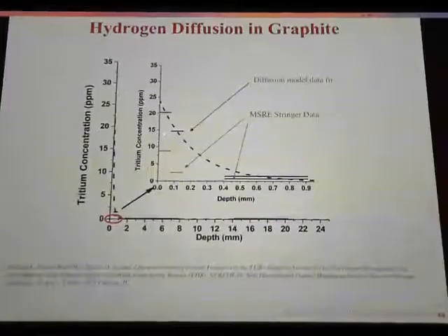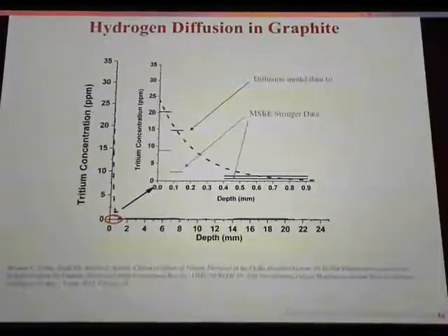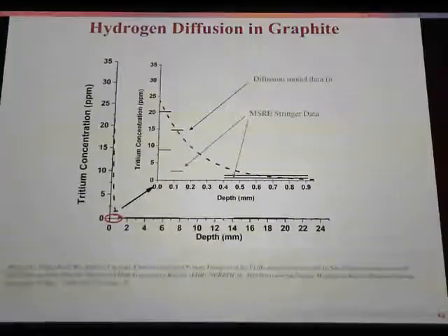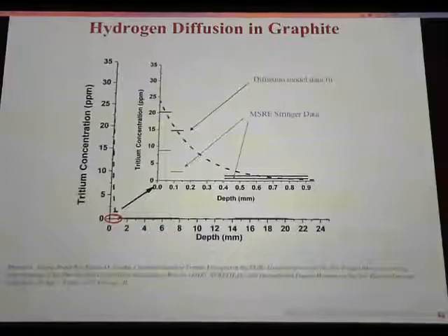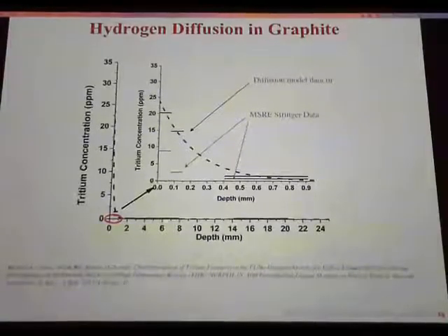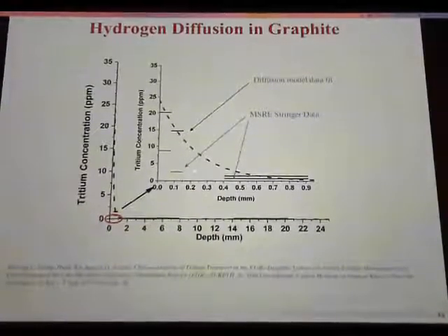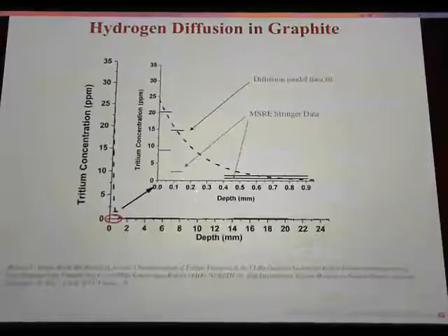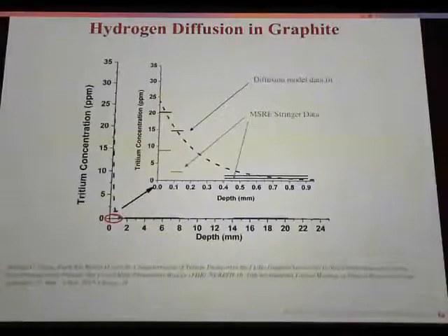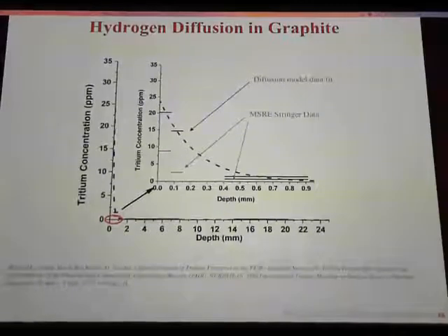And the answer is no, we cannot, because the shape that that profile has just does not fit the shape of a diffusion profile. What you have is a very flat gradient in the center and a very sharp gradient at the surface. So there are two choices. Either the graphite is not homogeneous, so somehow its diffusion coefficient is different in the outer 0.2 millimeters, 0.5 millimeter, or there's a different mechanism of transport that's happening. And it's possible that it's both.